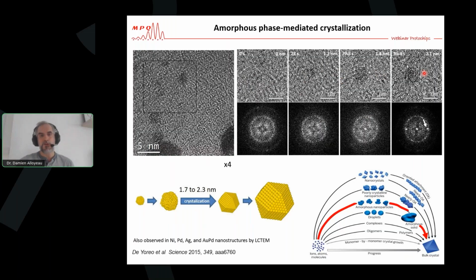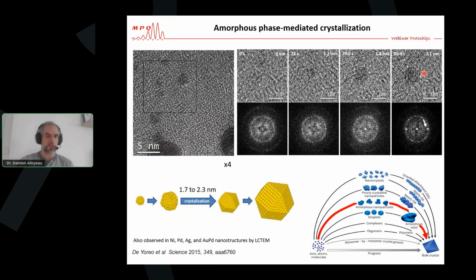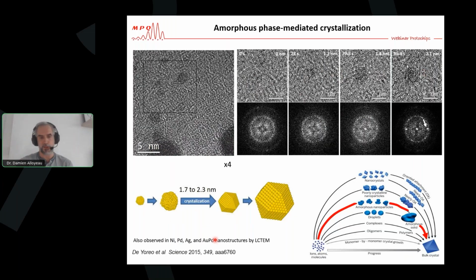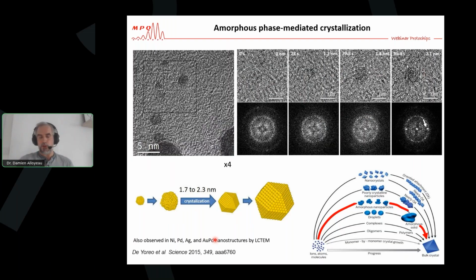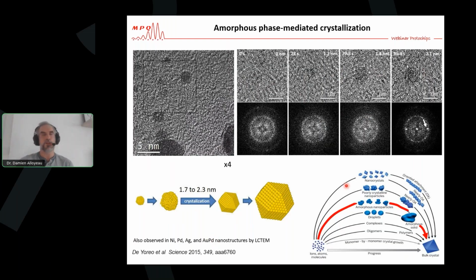So this type of amorphous phase-mediated crystallization has been observed in many other systems, nickel, palladium, silver, and even in nanoalloys. And it's also well explained in the literature that it is one of the possible non-classical nucleation pathways that you can see in the formation of nanostructures. So this result is not very surprising, but the question you may ask is: is this amorphous phase due to kinetics, meaning that you grow the nanoparticles too fast, and you have an out of equilibrium amorphous phase?